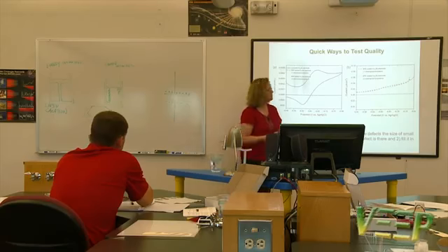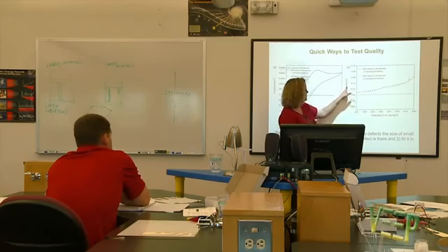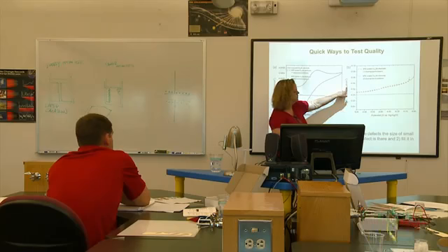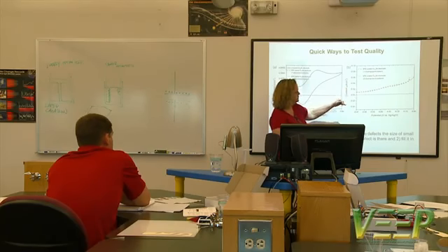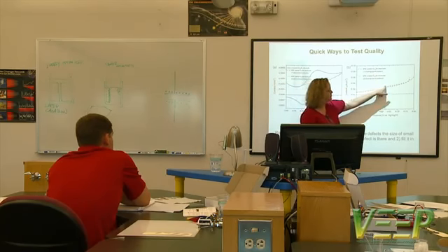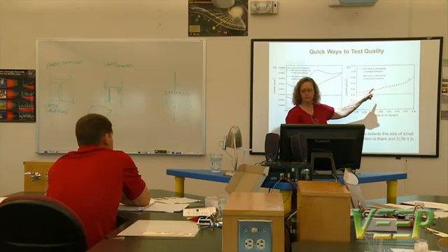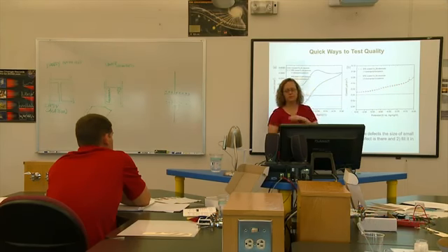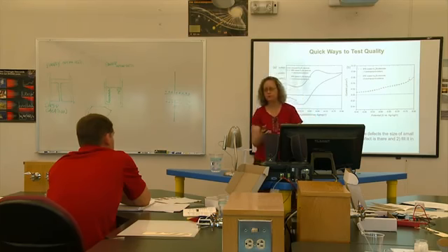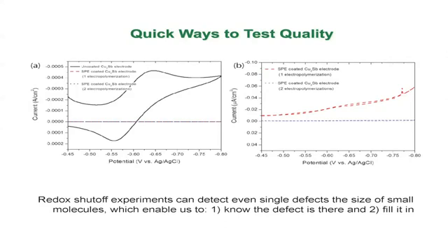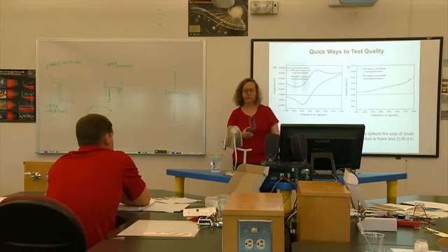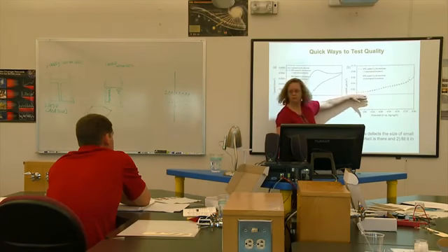Now, this is what I mean by really sensitive. So now we're at microamps. After the first polymerization, you do see a tiny bit of this shape. It's not a real duck shape, so we know it's not a real pinhole defect, but what it means is that there is somewhere on this whole electrode that's thin enough that the polymer is diffusing through and could be a weak spot. So we polymerize again, one more cycle, and then it goes to zero.